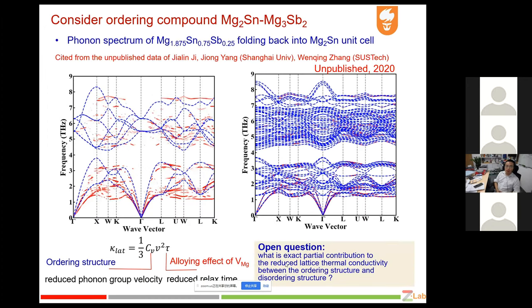And at the same time, we also did some phonon spectrum calculations for this material, considering the coexisting magnesium vacancy and the substitutional defects. In this calculation, we realize the phonon velocity is reduced. Generally, in our calculation we can consider the vacancy as a kind of ordering compound between magnesium tin and magnesium antimonide. And at the same time, we also see the disordering alloy effect also reduces the relaxation time, also contributing to the reduced lattice thermal conductivity.